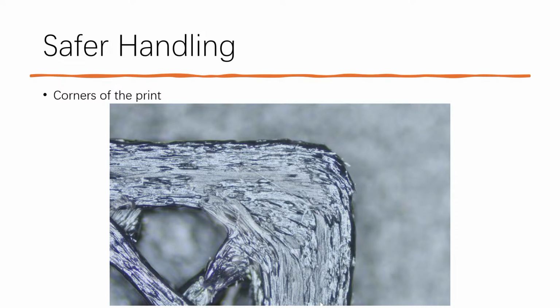And there are also some other issues when you have the fibers facing out. If your print has a lot of corners, you can see the fibers are stiff. If you turn a corner, I apologize for the picture, but if you look closely, there are actually small fibers sticking out, because when it turns, the fiber doesn't turn. It will come out, and you have to watch out for corners when using fiber filaments.